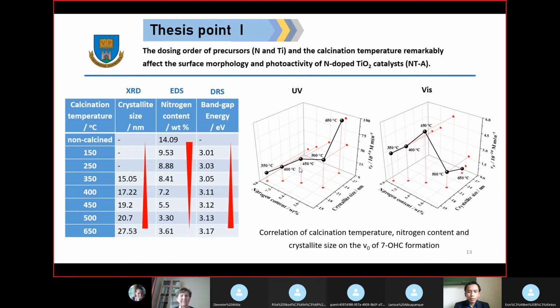To study the effect of the calcination temperature on the photoactivity, we made this figure, where we clearly see that under UV the photoactivity increases with increasing calcination temperature. It strongly relates to the crystallite size: the higher the calcination temperature, the higher the crystallite size, and also the photoactivity. Under UV illumination, the band gap energy relatively did not affect the photocatalytic activity, because the energy of the UV light is enough to activate the catalyst even at a higher band gap energy.